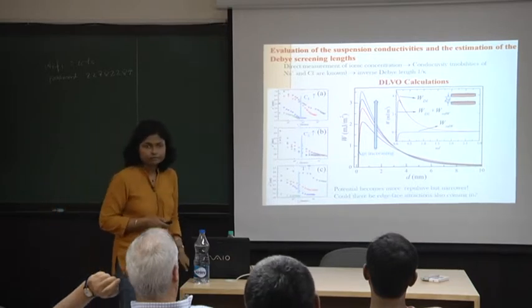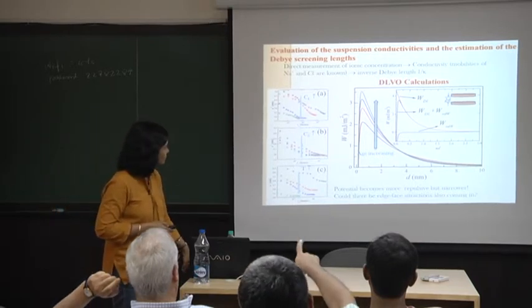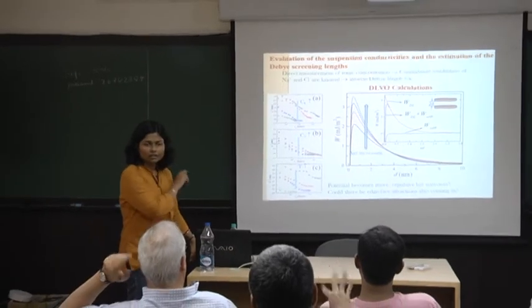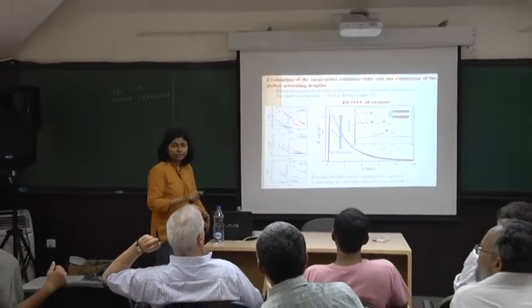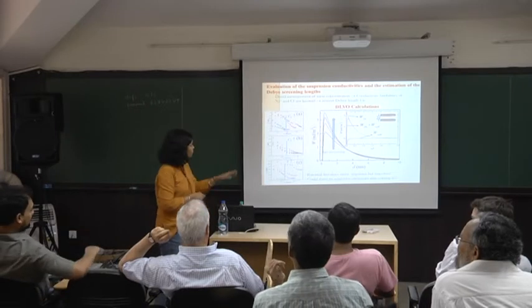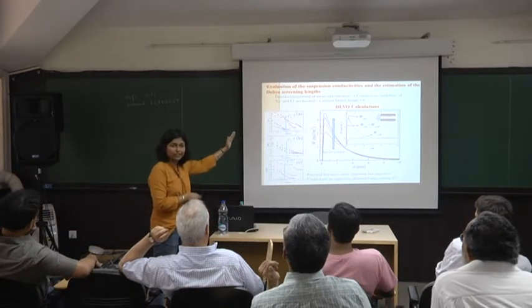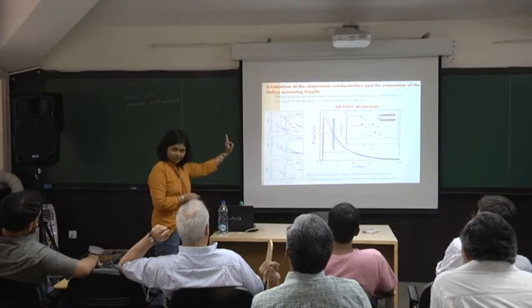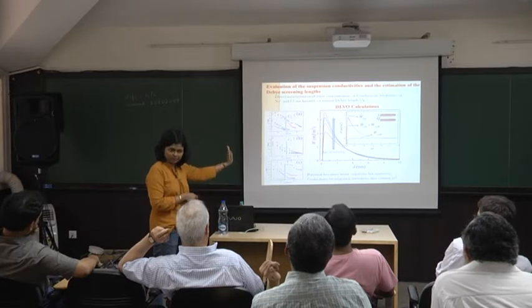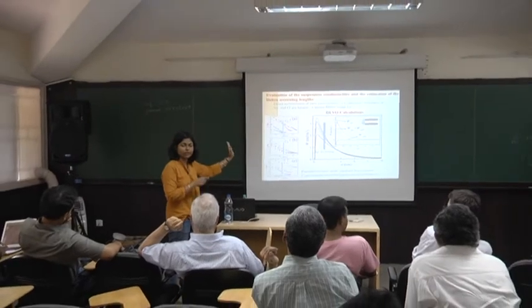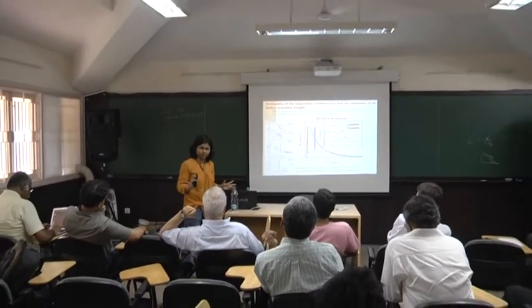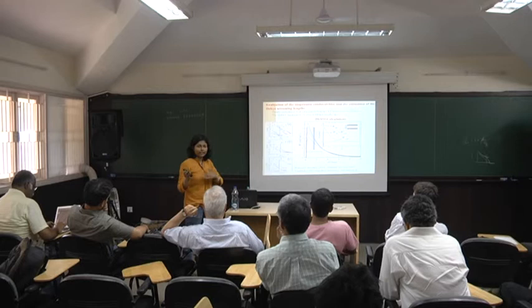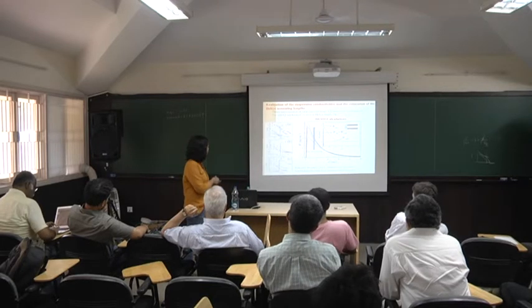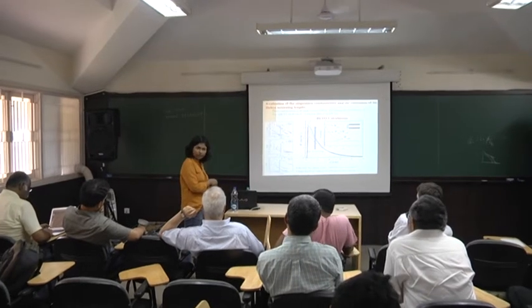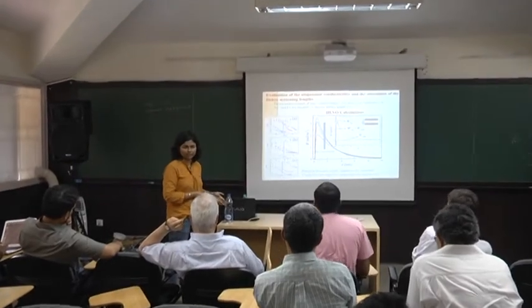No further exfoliation where you do this. There are no more discs being added to the suspension. These are all for the same number of discs. What is happening here is because of the number of sodium ions in the solution, because the only external parameter that we've used here is the Debye length, which we calculate from the sodium ion concentration.